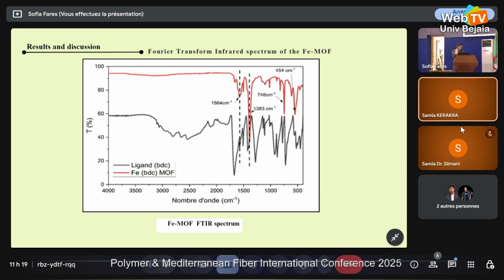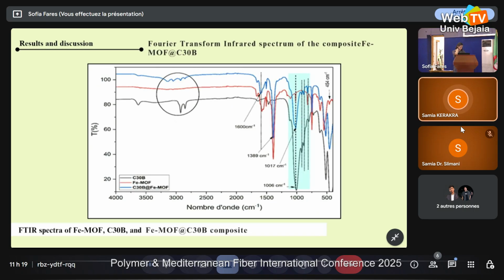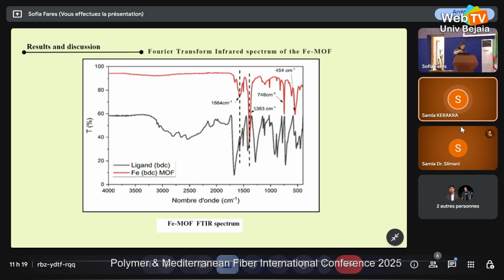The second one, the 1383 band, typical for carboxylate in a coordination complex, further confirms the coordination of iron with the ligand. And another band that is very important is at 748, likely related to aromatic deformation or Fe-O bending modes in the MOF structure. So based on these results, we can say that the synthesis of our MOF was successful.